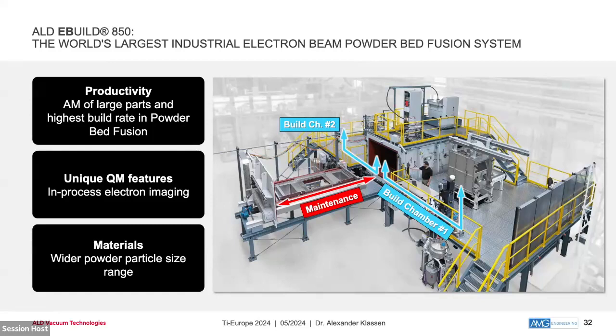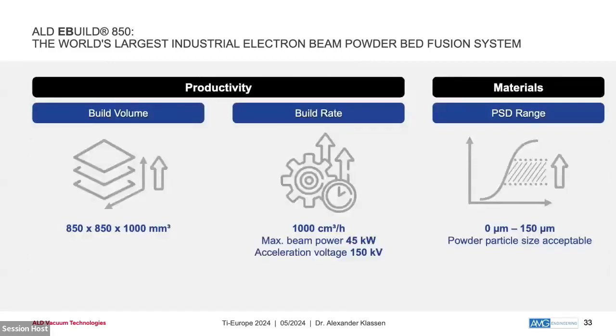Put into numbers, we have a build volume of 850 by 850, the area, and a build height of up to 1 meter. We can reach build rates of up to 1,000 cubic centimeters per hour, which pretty much competes with laser beam systems having 16 to 25 lasers operating in parallel. And what's more is that we can use the whole particle size range between 0 and 150 microns without having any disadvantages when applying the powder.